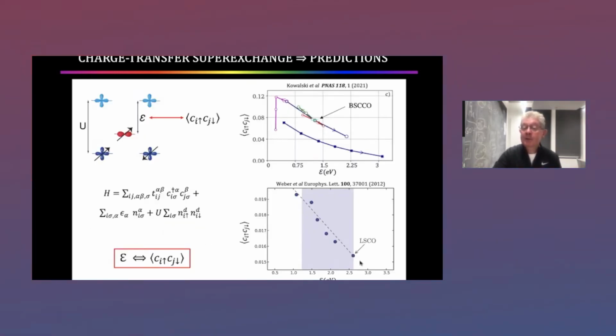Okay. So for lanthanum cuprate, this was done by Weber, Haule, and Kotliar. They adjusted the charge transfer energy, and what they found out is the pair wave function amplitude changed very rapidly as you change the charge transfer energy. You're not changing temperature, you're not changing the carrier density, you're just changing the charge transfer energy, but it has a huge impact on the superconductivity.